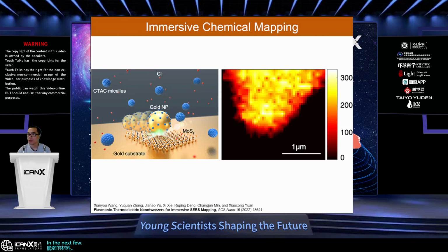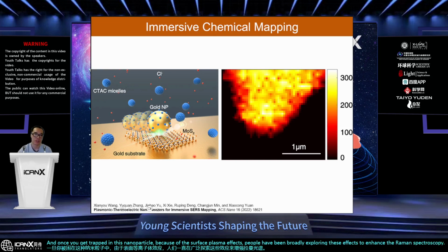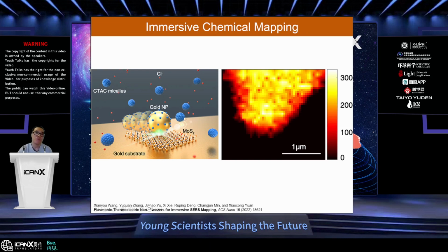In the next few slides, I will show you a few examples of application of these opto-thermoelectric nanotweezers. This was demonstrated by Professor Yuan's group in China, and they're using this opto-thermoelectric tweezer to trap gold nanoparticles, since this is applicable for all sorts of particles. And once you can trap these nanoparticles, because of the surface plasmon effects, people have broadly explored these effects to enhance Raman spectroscopy, which we call surface enhanced Raman spectroscopy. So they demonstrate that since you can use a laser beam to manipulate the particles through the opto-thermoelectric effect, you can move this around as a Raman prober.